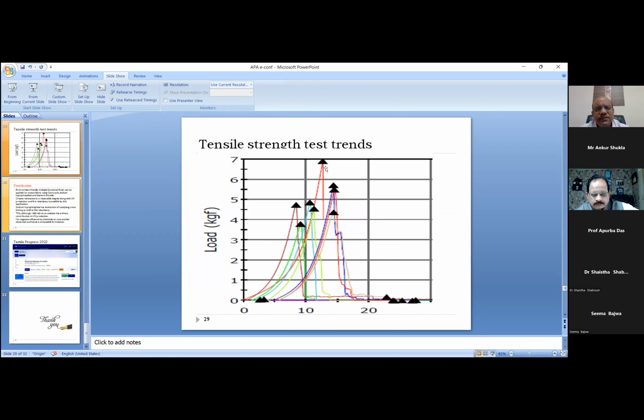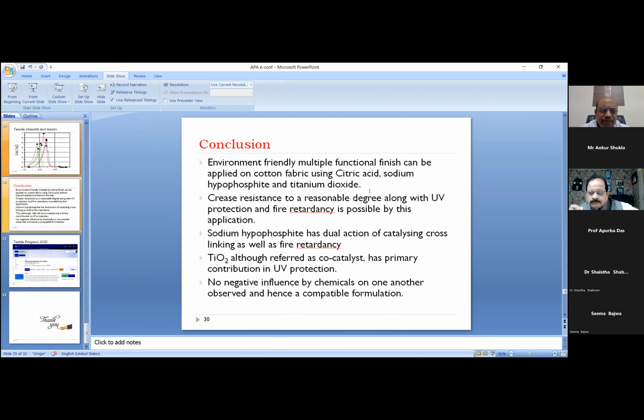And the tensile strength, there was some reduction in tensile strength. This shows the untreated sample, the rest are treated samples. So there is some reduction in tensile strength, but still the reduction didn't harm the total strength of the material, because cotton as such is a high strength fiber. So that much reduction is not going to actually affect its use. In fact, if you use DMDHU, the extent of reduction in strength will be much more. So now coming to conclusion, an environment-friendly multiple functional finish can be applied on cotton using citric acid, sodium hypophosphite, and titanium dioxide.